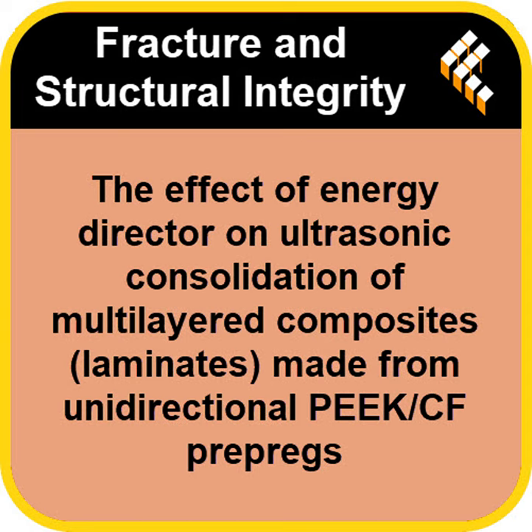And the samples that were supposed to be helped by the energy director? A total mess. Total non-uniformity. We're talking layer curvature, big voids, and even signs of localized failure. Especially at those longer times, 800 and 1200 milliseconds. So this is where the ED fails spectacularly. It does. But why? I mean, if it's designed to melt first, why is it causing all these structural problems?